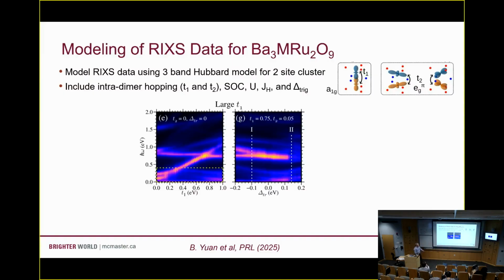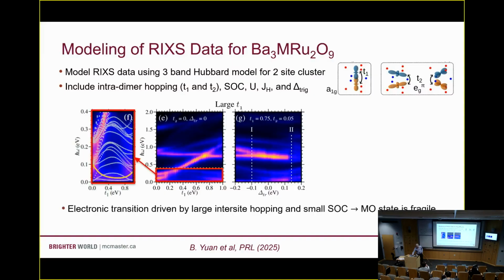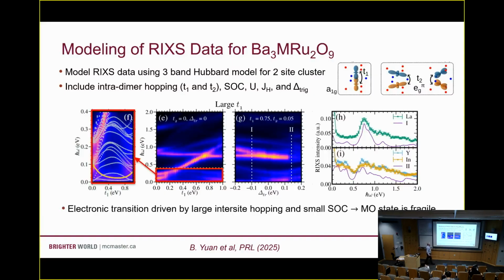Okay? So if we pick parameters here, we're calling this point I, or point II, or 1 and 2, then we can simulate the RIXS spectra, so no extra parameters added here, except an overall amplitude, and we get something that looks like lanthanum, something that looks like yttrium and indium. Okay? So this is pretty good without adding too many extra bells and whistles.